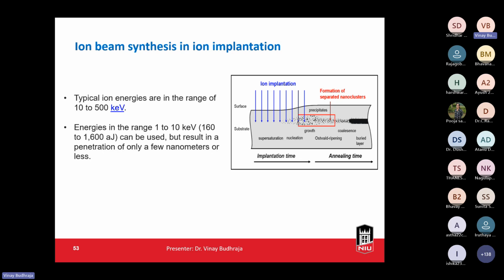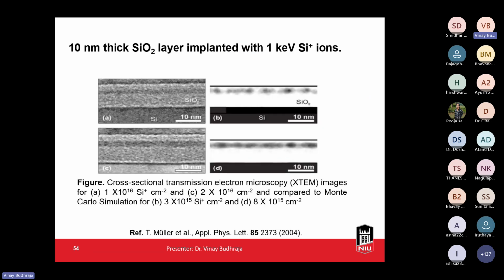Overall, it is available from 10 to 500 kilo electron volts. In the processing range, mainly 1 to 10 kilo electron volts is used. I have used ion implantation in one of my processes when I was fabricating solar cells, and we used around 5 kilo electron volts to create the dose for the p-type silicon wafer.